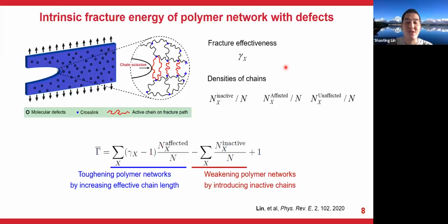So far, we have identified the fracture effectiveness of each type of chain. And we're also able to quantify the number densities of different types of polymer chains. With that, we are able to calculate the intrinsic fracture energy of a polymer network, which is basically a mean value of energy considering the effect from the different chains. So here is the general expression. The first term describes the toughening effect due to the effectively longer chains, since the fracture effectiveness, as I mentioned, is always greater than or equal to 1. And the second term is always negative, which describes the weakening effect due to the presence of inactive chains.